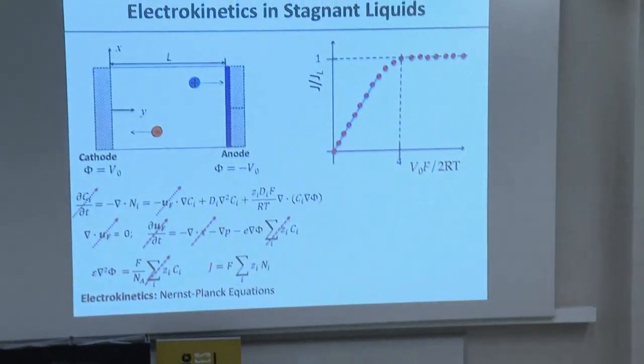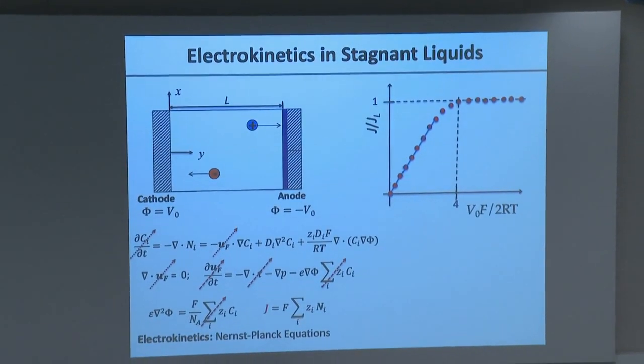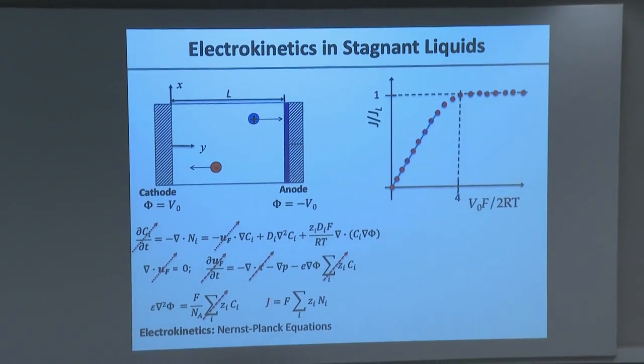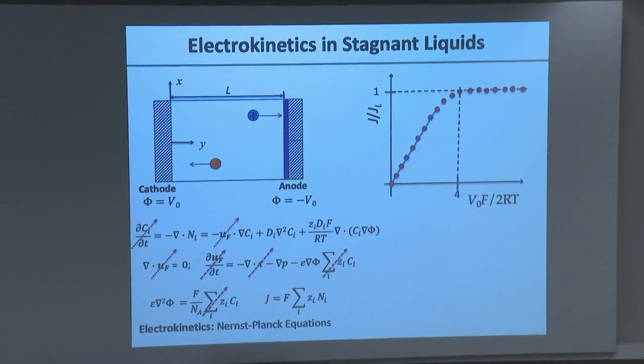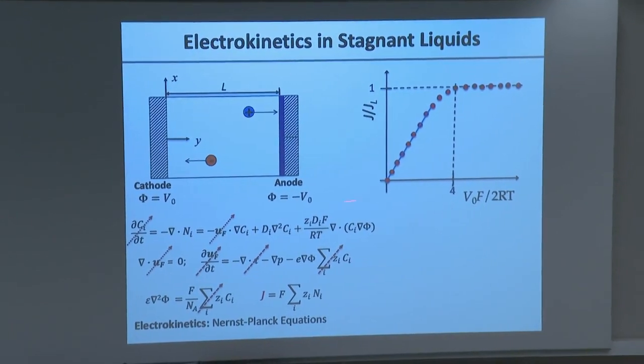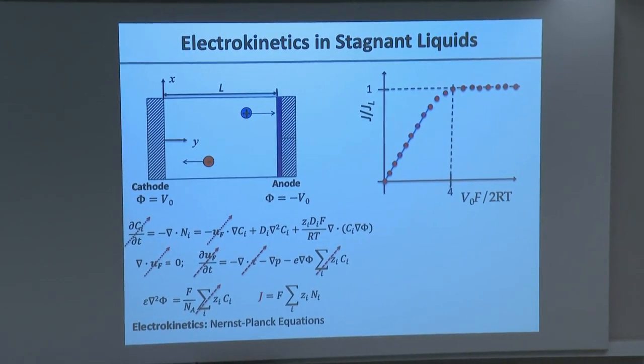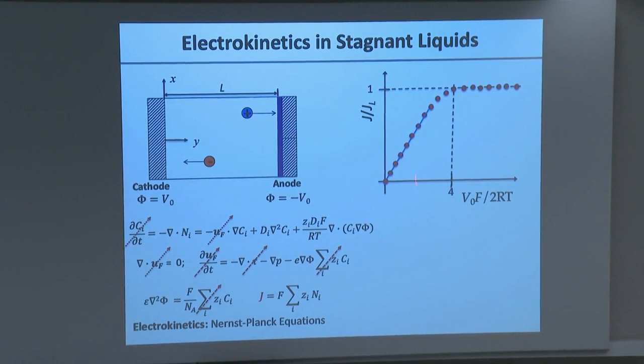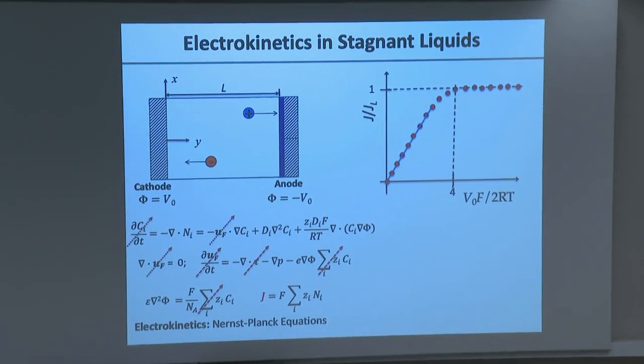Now, when you do that, you get a very nice and interesting solution to this problem that's illustrated on the right, where I plot basically the flux of ions, or a current, J, as a function, in this case, of the potential, V, that I apply. In other words, the driving force. What we find is that the current at low potentials is actually proportional to the potential. This is a so-called Ohm's law-like response, right? V is equal to IR. So the current just responds in proportion to the potential.